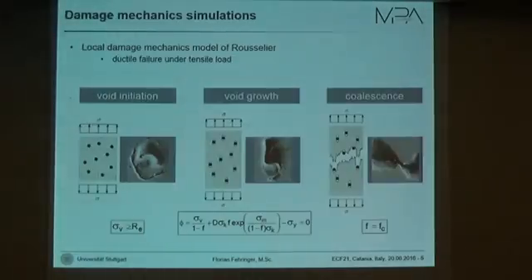For the damage mechanics simulations, we are using the local damage mechanics model of Rousselier. The Rousselier model is for ductile failure under tensile load. And ductile failure under tensile load can be described by 3 different stages. First we have void initiation, which happens as soon as our equivalent stress reaches the yield strength. After void initiation, we have a growth of the voids, which is described by the Rousselier model and is strongly dependent on the hydrostatic stress. And at the end, when the void volume reaches the critical value, we have a coalescence of the voids, which finally leads to the fracture of the specimen.